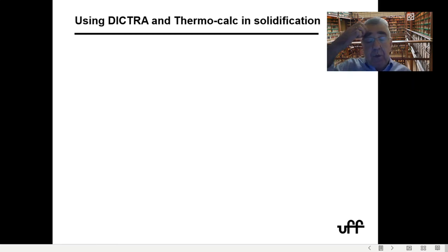Now, when you try to add these very expensive or more expensive microalloying elements in steels, you have to be careful because sometimes you have significant losses, not only in steelmaking, but also in solidification. You can see titanium nitride precipitating as relatively large particles. You can see sometimes even niobium and vanadium being present in these particles. So one of the important things is to model what is happening during solidification so you can better design your alloy to avoid this.